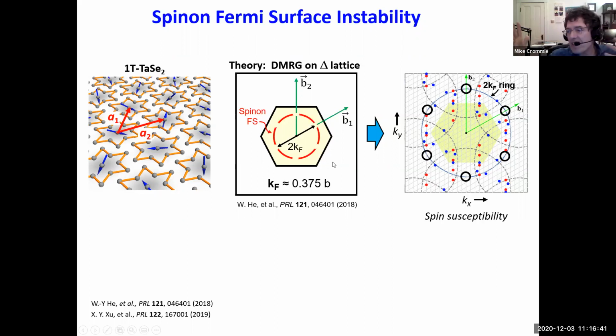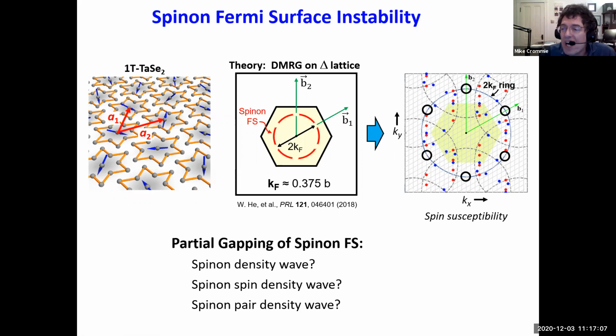Now, that's not so crazy because we often see partially gapped Fermi surfaces in solid state physics for electrons, at least. For many charge density wave systems, you have partially gapped Fermi surfaces. And so the implication of this calculation is that we should have a partially gapped spinon Fermi surface, where it's gapped in these particular directions, according to their prediction from a couple of years ago. And so you can ask what might cause this partial gapping, and there are several possibilities. For example, you could have a spinon density wave, or a spinon spin density wave, or a spinon pair density wave. It turns out that all three of these possibilities lead to the same answer for the STM. But we believe that the spinon pair density wave is the most likely explanation.